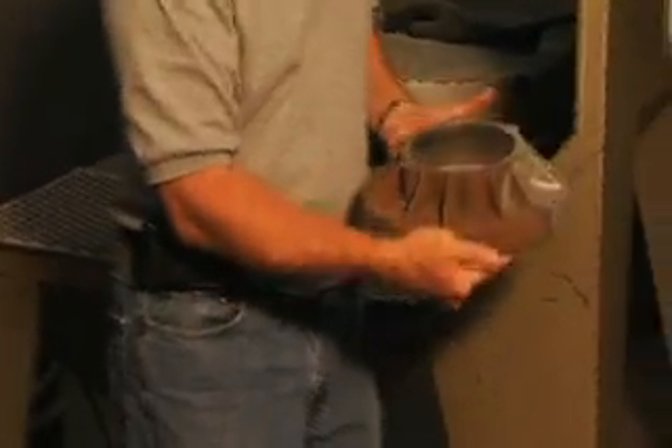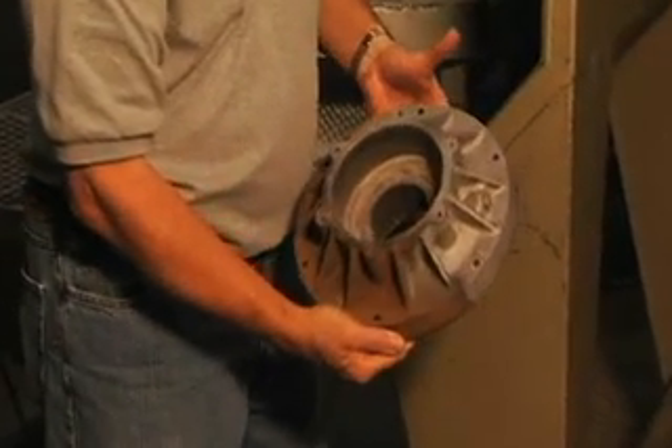This is an example of abrasive blasting with aluminum oxide. This is used primarily to clean surfaces of oxidation and to prep surfaces for coating. This sharp abrasive will provide the tooth anchor pattern to hold the coating to the surface.